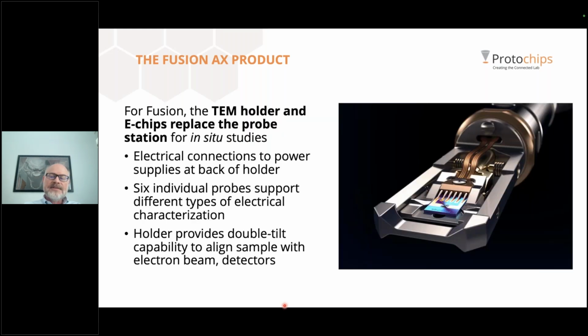Now, the part of the system that I think is most different from standard characterization is the combination of holders and chips. The TEM holder and chips replaces the probe station for in situ studies. Probe stations are usually large benchtop units that don't have to worry about space, but to fit in the TEM, we have to miniaturize the whole thing to fit into a pole piece gap less than 2 millimeters thick.